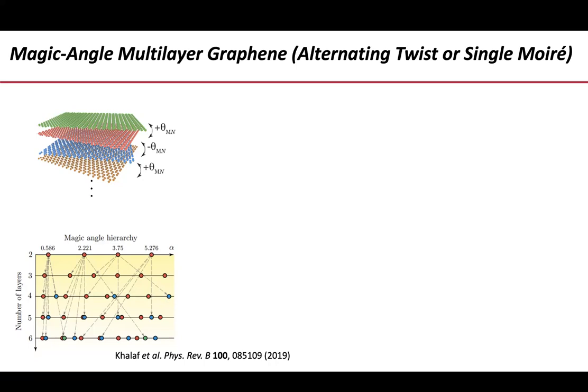No one has seen these. We don't know if those are robust versus things like atomic relaxation and other things that happen when you go to very small angles. The theory says that there are these. And then for three layers, another series of them. So you have the first magic angle, second magic angle, third, et cetera. At four layers, this thing splits and you have the red dot and the blue dot. So you have the first magic angle, the first second magic angle, the first third magic angle, and you also have the second first magic angle, the second second, the second third. And this thing splits, like a braid, and it just branches and splits to infinity down there. Each of these dots has different electronic structures, different topological structures, et cetera. I've concentrated on this dot and this dot, and I'm going to tell you about them, but there are hundreds of dots there to explore.